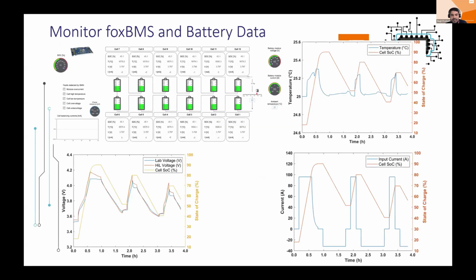So here I will tell about the results obtained during these experimental setups. The first one is the graphical user interface that we made to monitor the BMS data. Here we model 12 cells that are connected in series. Each cell shows the voltage, temperature, SOC, and the imbalance current that is flowing with each cell. This is changing according to this CCCV profile. In this test, we use a CCCV profile that was supported by Corvus, which was a maritime profile. Currently here it is constant current at very high rapid charge, and then constant voltage for the safety of the cells.